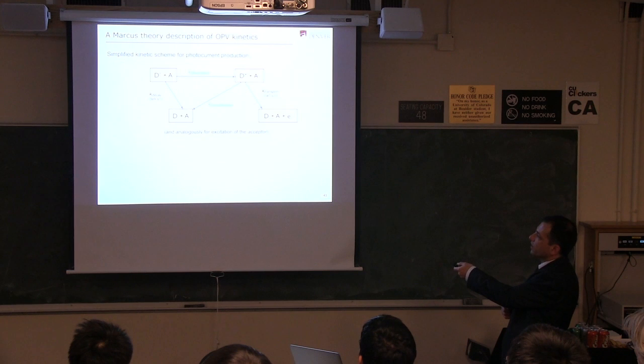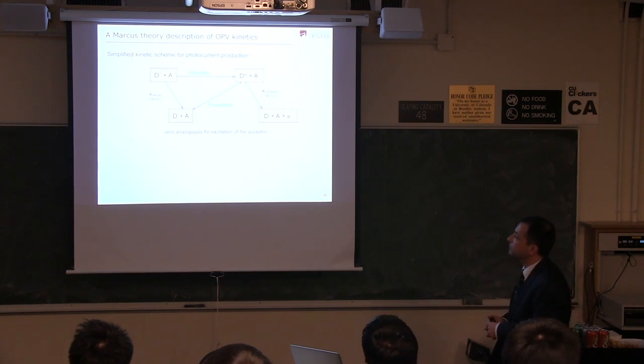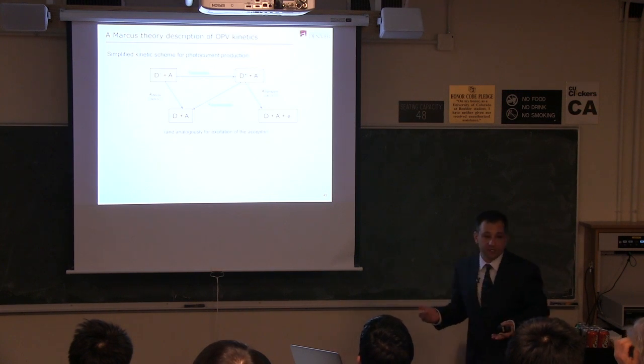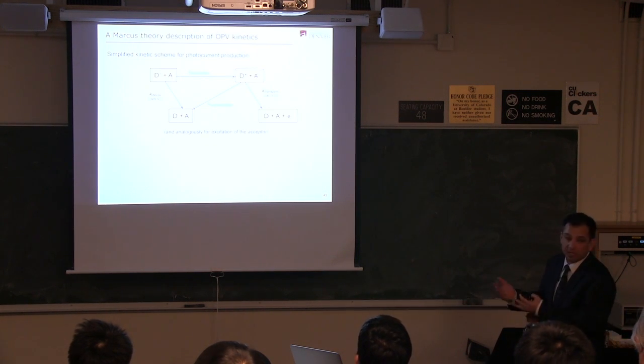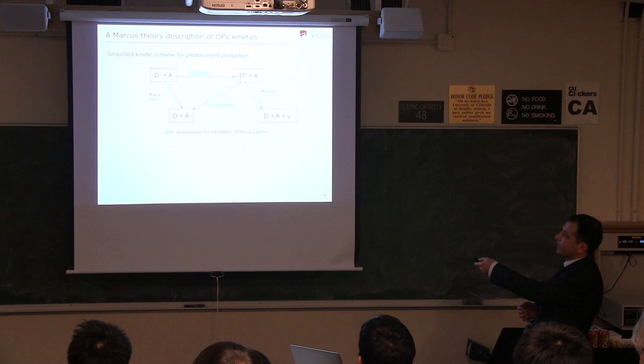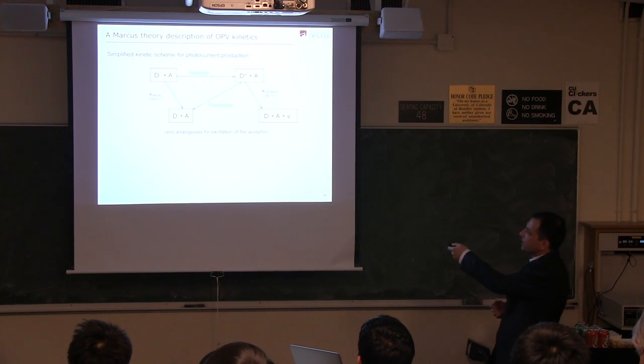We've given off a photon here. That's a loss mechanism. We can recombine from the charge separated state to the ground state. Or ideally, the process we want is that we can transport electrons out of the device. Each of those processes has a rate constant that we can determine. We measure this rate constant, that's about 300 picoseconds of lifetime. We can measure this time constant, that's about 10 microseconds of lifetime.